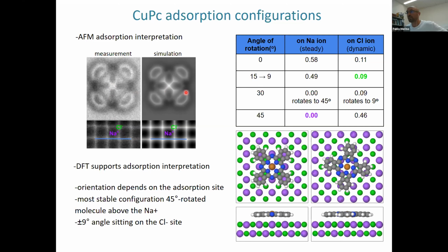We also did, well, actually, this was in collaboration with a group of Pavel, and he may know better than I do, but we did the simulations, and well, the agreement is quite remarkable. We also did the DFT of the system, and what we found is that, again, good agreement with our experiments, that the orientation depends on the adsorption site.